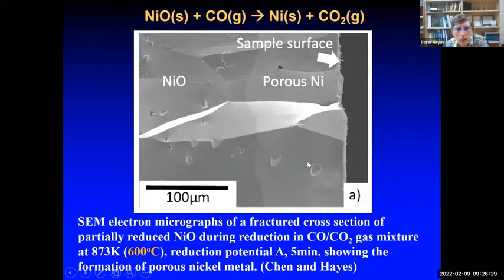If we look at 600 with a high CO2 ratio, then this is the original surface of the sample. Now we're looking at a cross section. We can see that these instabilities have moved in a reaction front all the way into the dense nickel oxide here. So this is porous nickel and this is dense nickel oxide.